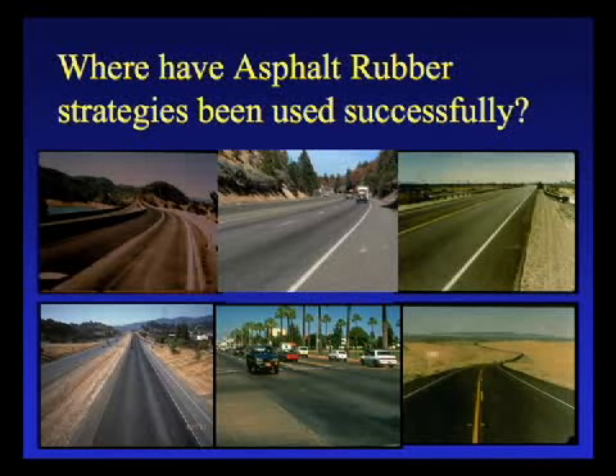Wide range of usage. We looked into the dry process, but we had very poor success with it. This is after just a couple of years over a concrete pavement. We had extensive cracking and potholing. We had areas that raveled very badly. We had areas that rutted and potholed. This caused us to move away from the dry process and strictly look at the wet process at Caltrans.